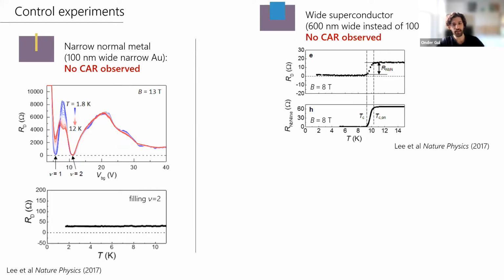In this case, the signal is effectively zero below the superconducting transition temperature around 9 Kelvin. We can also remark that there are no oscillations or fluctuations in the non-local signal in this magnetic field range, and for the interface length around 1.5 micrometers in this case for niobium nitride superconductor. These points will be extensively discussed in the next talk, but it may be useful to note the different features in a more or less similar geometry.